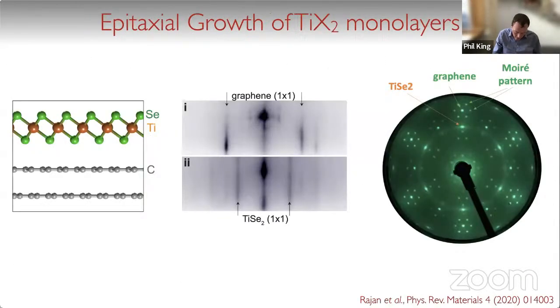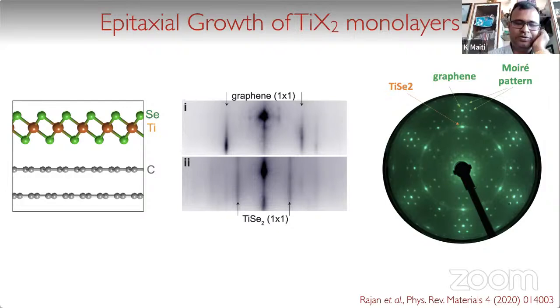If you look at the RHEED here, you see that the lattice constants of, I'm showing you titanium selenide here, but it's the same in titanium telluride, the lattice constants of the monolayer are rather different to the lattice constants of the graphene, and because it's van der Waals epitaxy, you grow the monolayer fully relaxed already in the first layer of growth. And so we do have the Dirac points of graphene that are also visible, but these are just further out in momentum, and so we're not seeing them in the spectra that I showed you here.